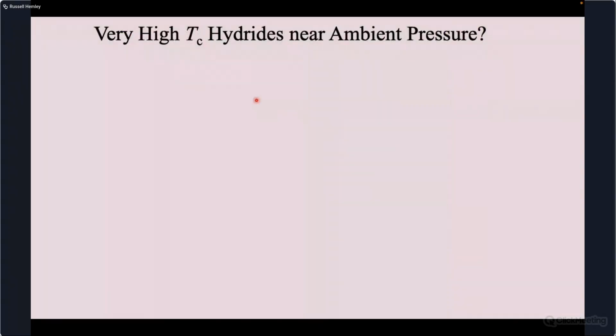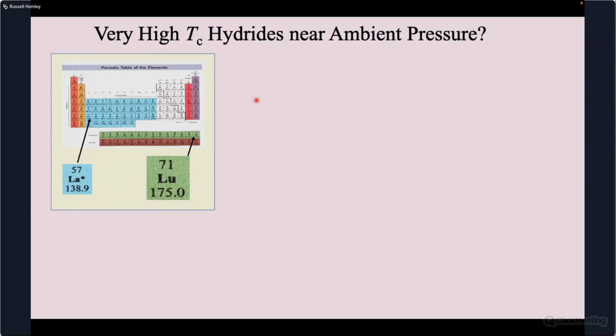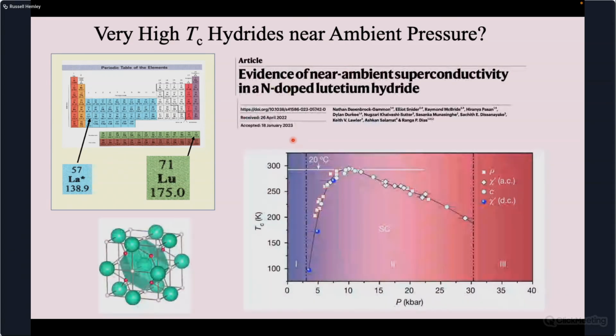So can we realize some of this remarkable behavior in hydrides near ambient pressure? Well, this is also a very active area of research in this field, and a lot of work has been done both theoretically and experimentally exploring this. I just want to take one example that we've focused on in the last couple of years, and that is looking again at the lanthanide series, but going from lanthanum over to lutetium, and following up on a remarkable report that appeared in Nature of room temperature superconductivity in a hydride of lutetium, measured with susceptibility and with resistance measurements, but at very low pressures, basically 2 orders of magnitude lower pressure than the superhydride work that I mentioned. The problem with this paper was it was retracted for a number of reasons, but we thought it was still worth studying this in detail because the data looked quite compelling.